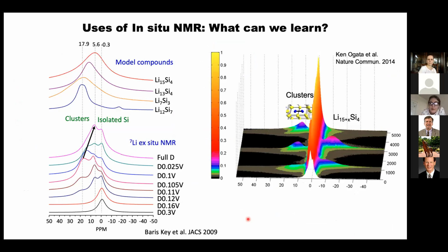And what we do when you have a reaction of lithium and silicon, you want to understand what phases will be formed. And so we go into the phase diagram, we find all the model compounds, we go and make them, and we learn what the lithium NMR spectrum of these different compounds would be, and try and relate the shifts that we see to the local structure.